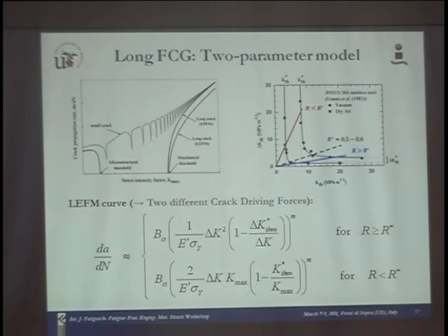You must have an evolution of the crack closure from the small crack to the long crack, and then you need to simulate that evolution until reaching a certain constant regime or constant effect of the crack closure. But of course, it affects the results, moving the crack propagation curve up and down, depending on the threshold you have.